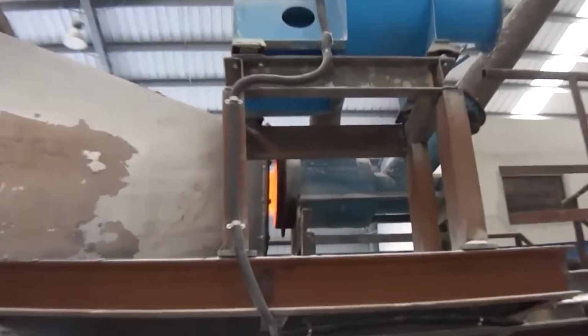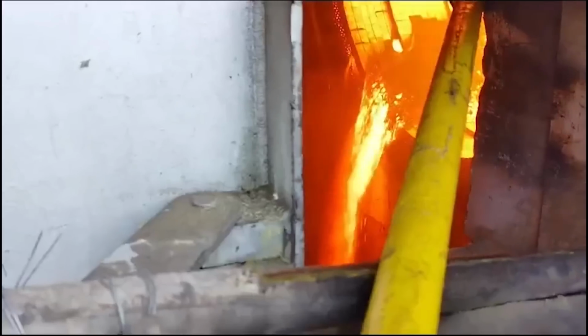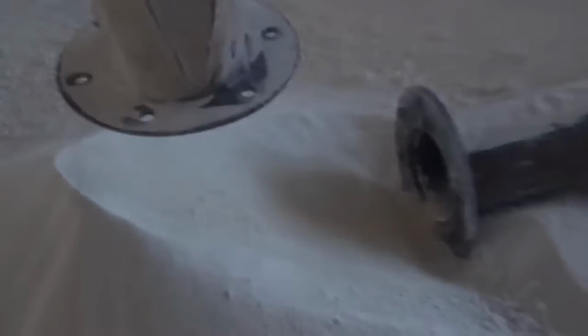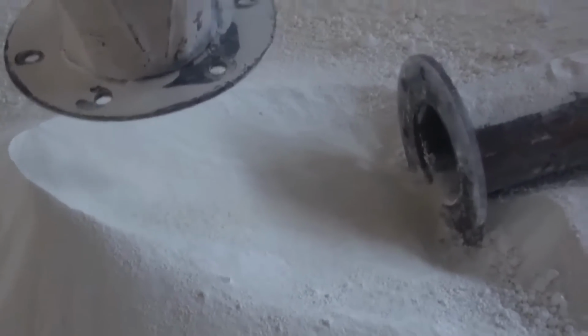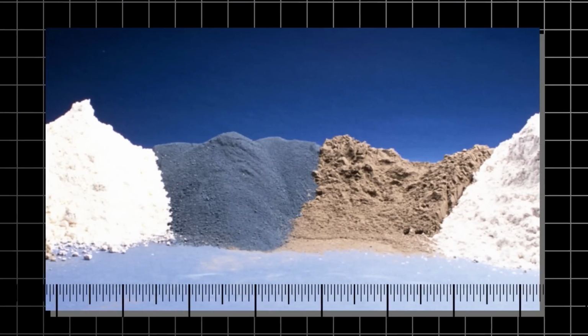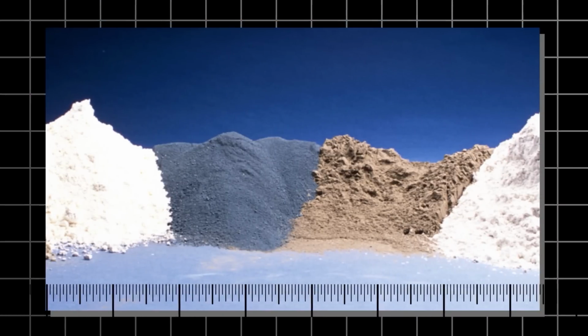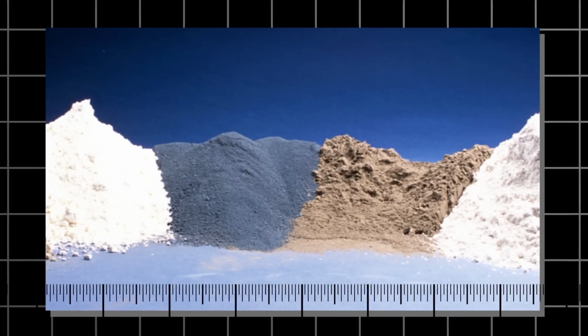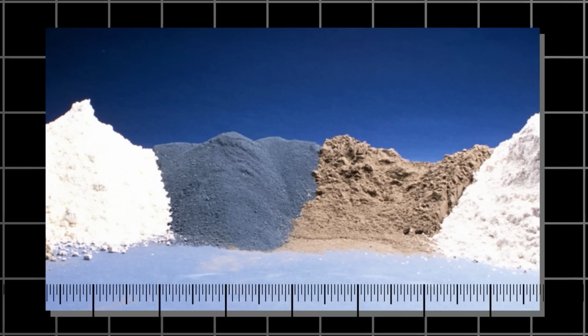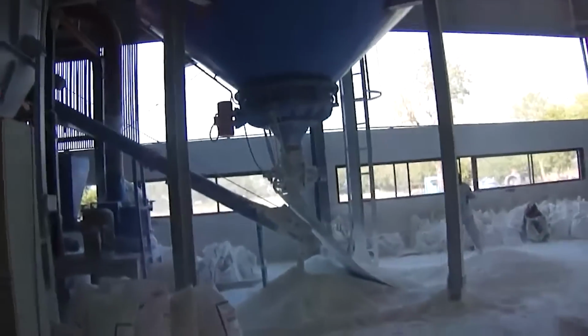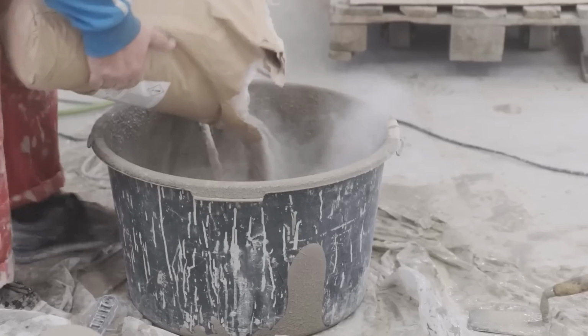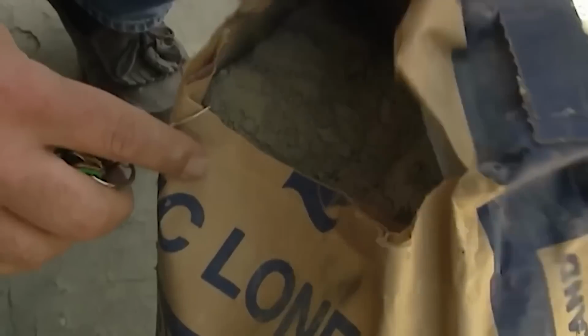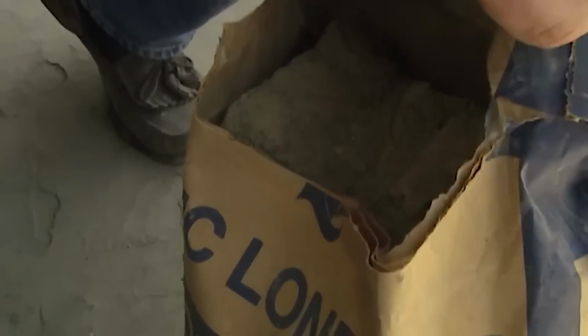Another mineral, dicalcium silicate, forms from calcium oxide and silica at higher temperatures and enhances the cement's long-term strength and durability. Additionally, tricalcium aluminate forms from calcium oxide and alumina, affecting the cement's setting time and early strength. Tetracalcium aluminoferrite, created from calcium oxide, alumina, and iron oxide, contributes to the color and overall performance of the cement.